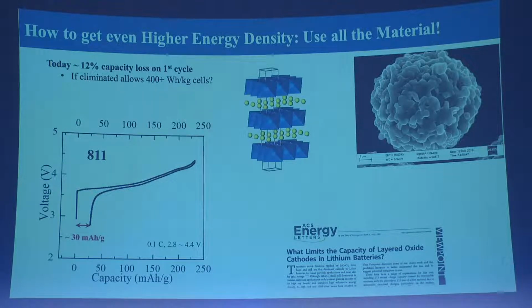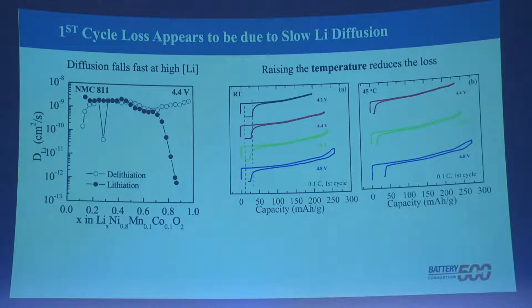Being a materials person, a chemistry person, the other thing we looked at for why it's not going back in is, is this diffusion controlled? And so we measure diffusion coefficients just using standard electrochemical techniques. And you see here, the solid points is the lithium going in. You can see it falls off the cliff after about 70% of the lithium going in. It's exactly the same as in this lecture hall. Okay, it's full about now. If some people come in and want seats, invariably the empty seats are in the middle. So everybody has to move. But the actual diffusion mechanism here is a divacancy mechanism. So you need, in fact, 2 vacancies. That means you need 2 seats empty for another person to move in. That's why it falls off the cliff so fast.